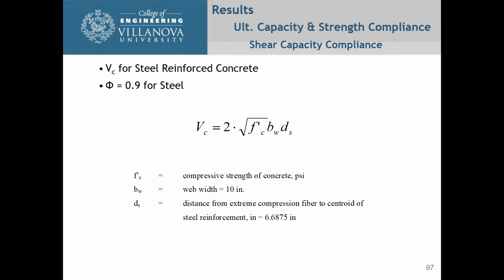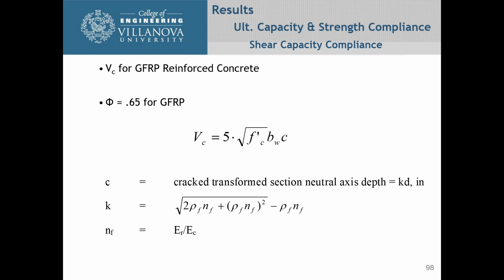So for steel reinforced, it's 2 square root f'c times the width times the depth to the centroid of the steel. That is the shear capacity of the concrete. And we have a phi factor of 0.9 for steel. For GFRP bars, you have a phi factor of 0.65, but now Vc is equal to 5 times the square root of f'c times b, which is the width, and then c is the cracked transformed section neutral axis depth, kd. And you can see below how you figure that out.